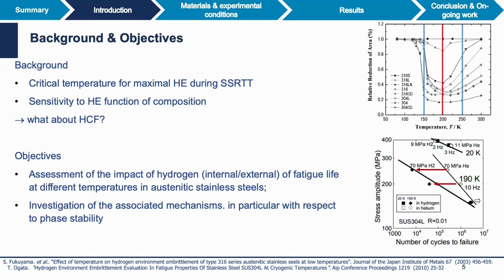So you've already seen this graph in the previous presentations, where you have the susceptibility to hydrogen embrittlement of different grades of austenitic stainless steels as a function of temperature. And what is observed is that during slow strain rate tensile tests, you have a maximum embrittlement around 200 K, maybe 190 K. And in addition to that, the magnitude of this embrittlement will also be highly sensitive to the chemical composition, in relation mostly with martensitic transformation. That means that you have small embrittlement in the case of stable alloys. And in the case of less stable alloys, such as 3 or 4, for instance, you have a large embrittlement at this temperature. But the question is also, what about high cycle fatigue?